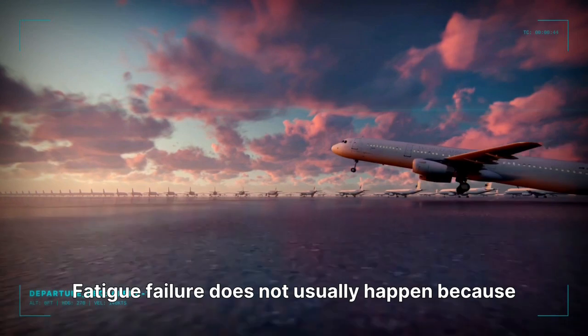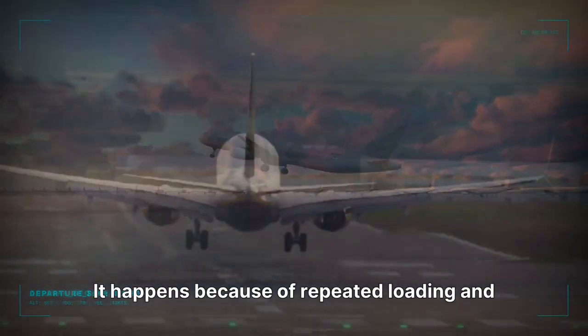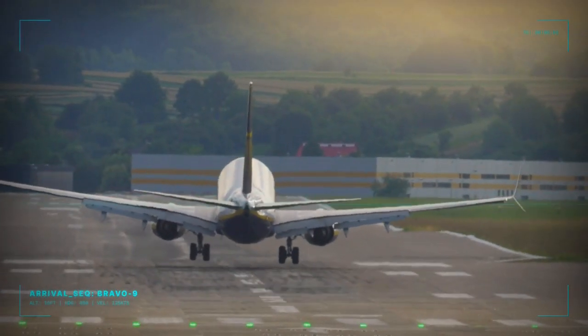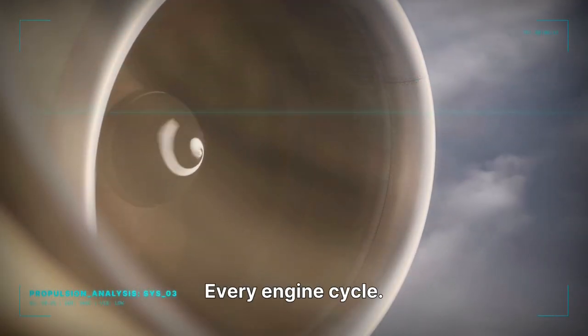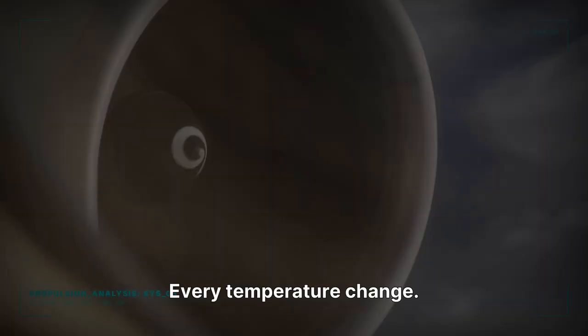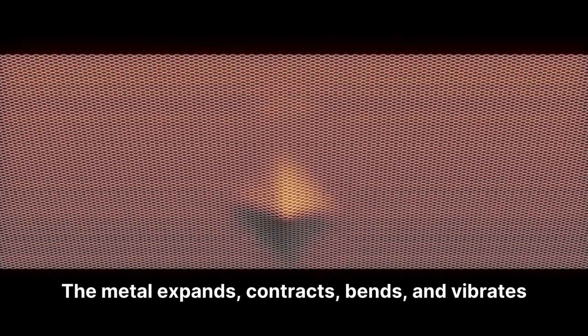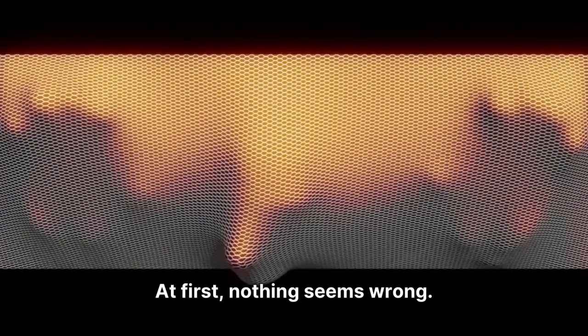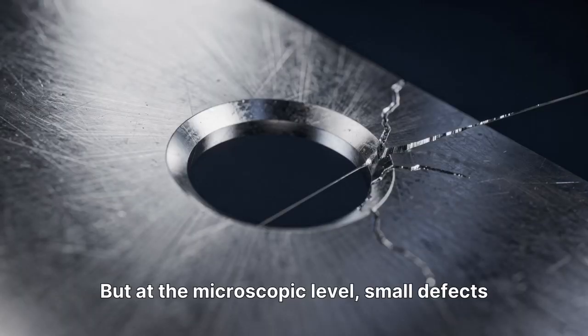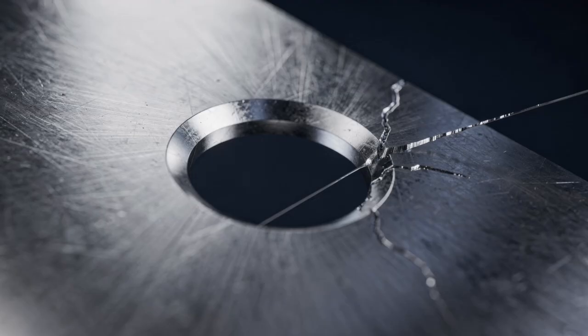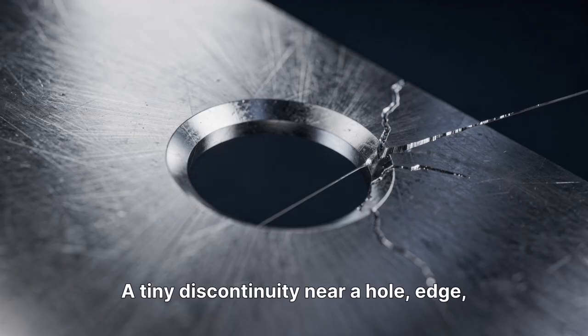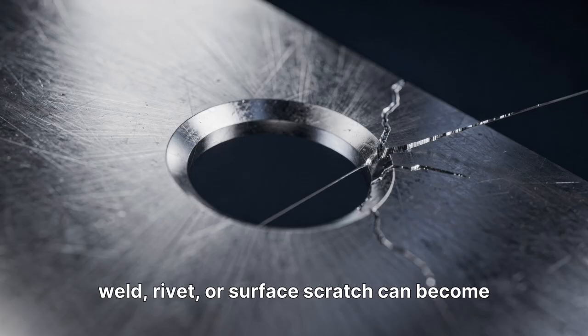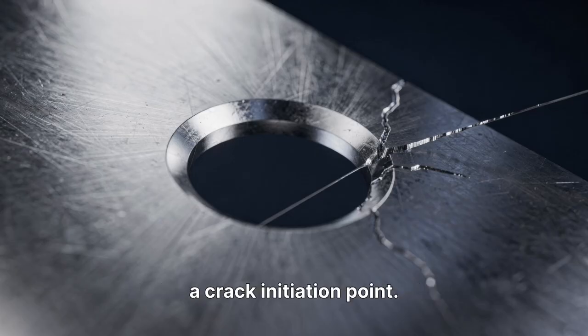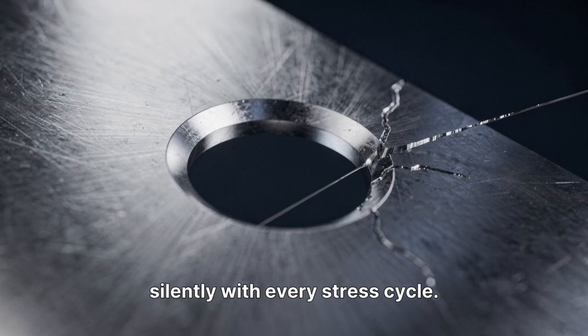Fatigue failure does not usually happen because of one big overload. It happens because of repeated loading and unloading, every takeoff, every landing, every engine cycle, every vibration, every temperature change. The metal expands, contracts, bends, and vibrates again and again. At first, nothing seems wrong, but at the microscopic level, small defects begin to grow. A tiny discontinuity near a hole, edge, weld, rivet, or surface scratch can become a crack initiation point. Once a crack begins, it can grow silently with every stress cycle.